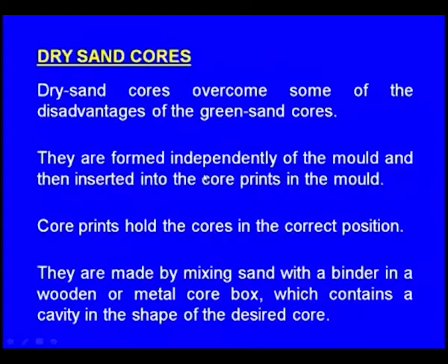Next, let us see the dry sand cores. Dry sand cores overcome some of the disadvantages of the green sand cores. First of all, green sand cores are not made separately. They are formed while we are making the mold itself. But the thing is, they have poor strength. So, when we make the cores with dry sand, the cores have additional strength. That is how they overcome some of the disadvantages of the green sand cores.